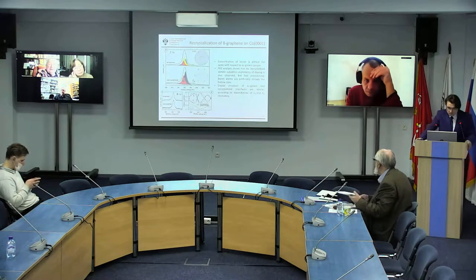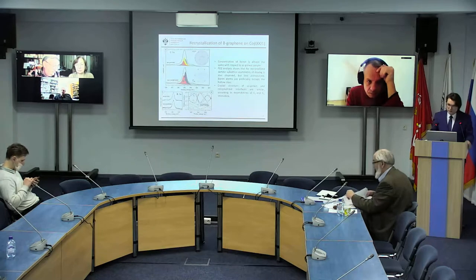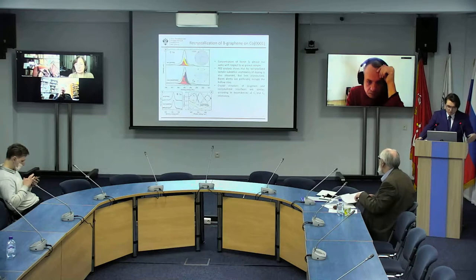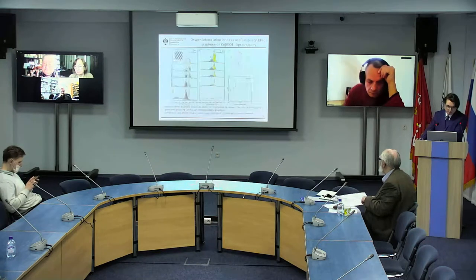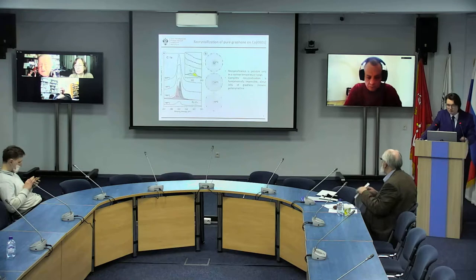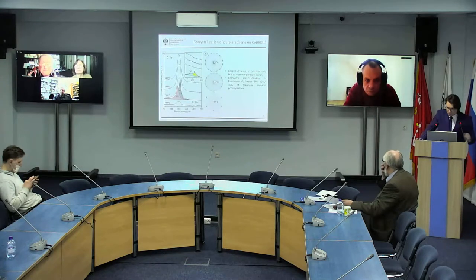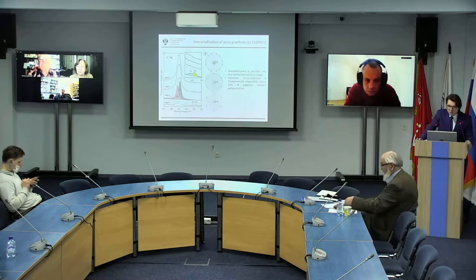As for this expansion, photoelectron diffraction is a well-known and powerful method for the analysis of the crystalline structure. I don't give the data of the spectrum here, but the fact that it's not a feature of expansion, but a real effect, is not questioned, because even if we give the appropriate graphene spectra, for example, in case of non-doped graphene, we see the breakdown, and we see that the intensities of these spectra change depending on the energy of photons at which we measure them.